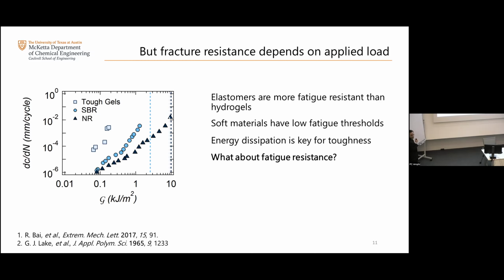The second observation that I'm hoping to show in this slide is that if you had elastomers, like for example SBR, which is a classic synthetic elastomer, styrene butadiene rubber, and you have natural rubber, the fatigue resistance of these systems is intrinsically larger than that of the gels, even though, for example, SBR has a lower fracture toughness than these gels. Okay, so it really seems that we understand that you need a lot of energy dissipation to make systems tough, but maybe energy dissipation is not really the metric that you want for making very fatigue resistant materials. Maybe there is something else, because clearly toughness and fatigue resistance are not necessarily very well correlated.